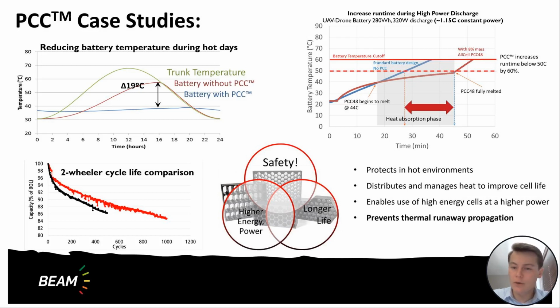The final case study we'll take a quick look at is for a drone application where you'll have constant high power discharge. And so what you can see here, as you start to elevate pack temperature through that high power discharge, the wax starts to melt, and you obviously maintain a uniform temperature. And so what you actually get is longer run time.